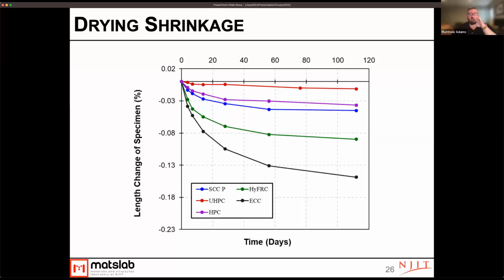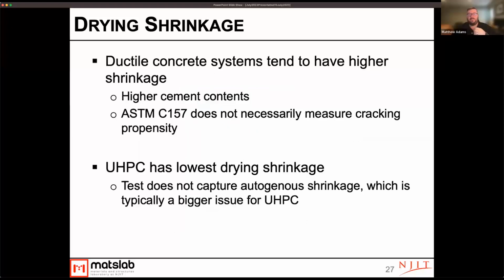But one thing to note is that even though those levels of shrinkage are higher, and that is generally due to the high cement contents, the test method that we used, ASTM C157, does not necessarily measure cracking propensity. It's just measuring free shrinkage. There's no restraint in the system. And other research has shown that these ductile concretes, while they do shrink a little bit more, they also tend to crack less because of the fiber content. And in this test method, the UHPC showed the lowest drying shrinkage. But this test method also doesn't capture autogenous shrinkage, which is typically a bigger shrinkage issue for UHPC than drying shrinkage is for UHPC.